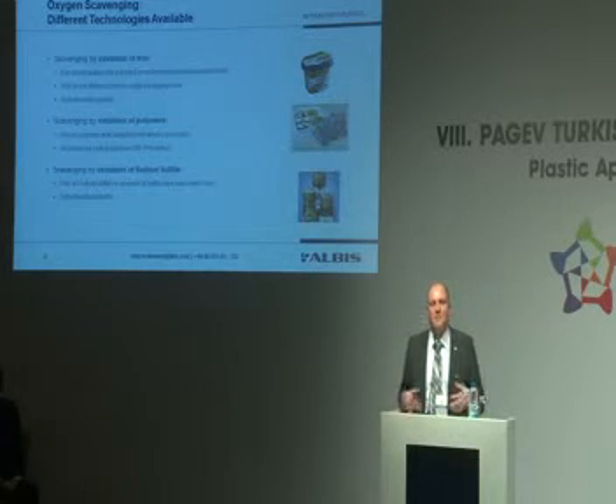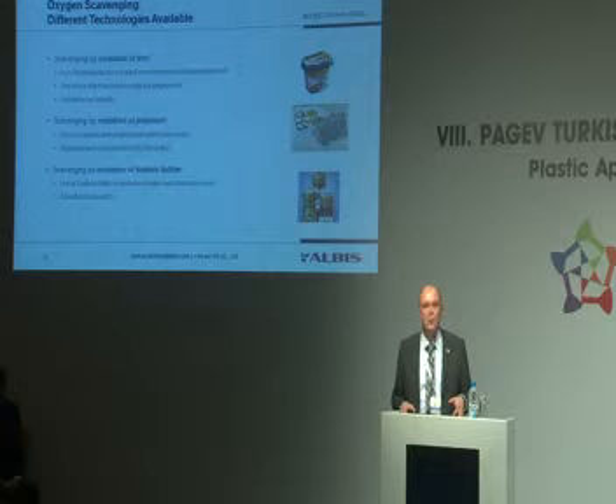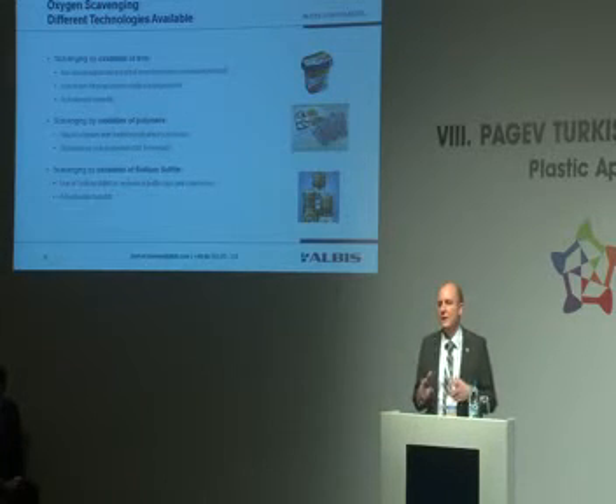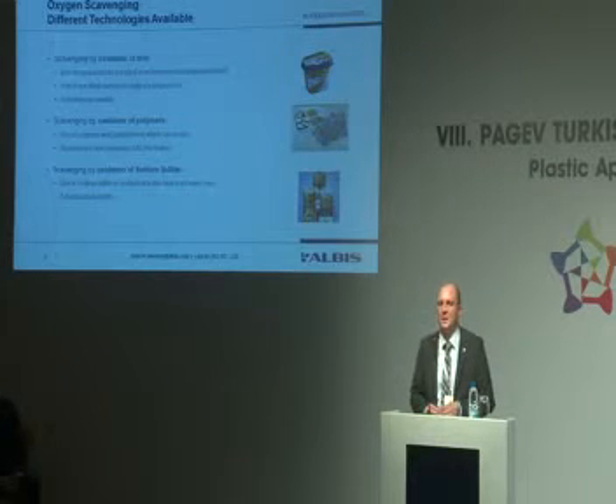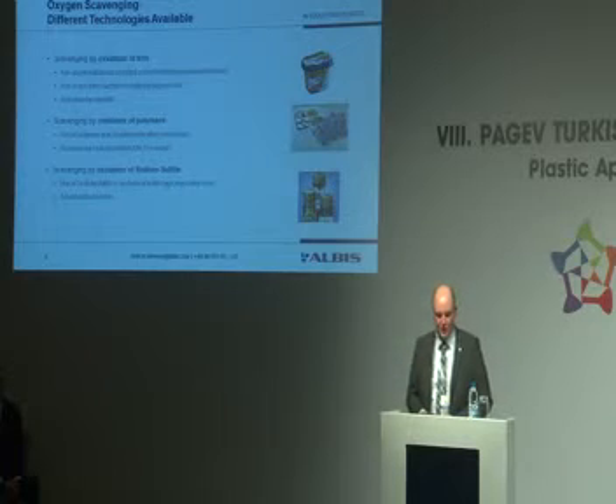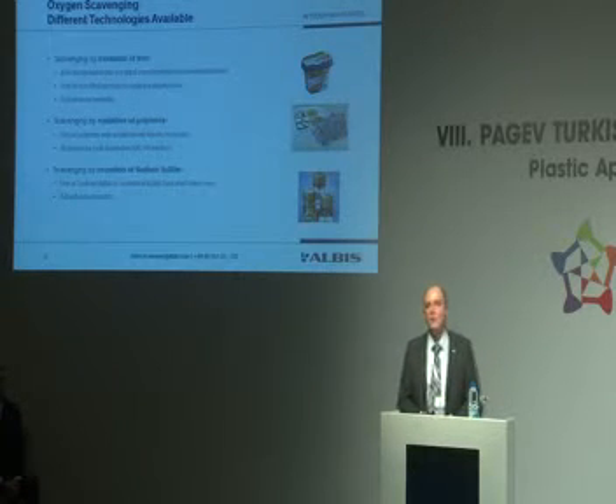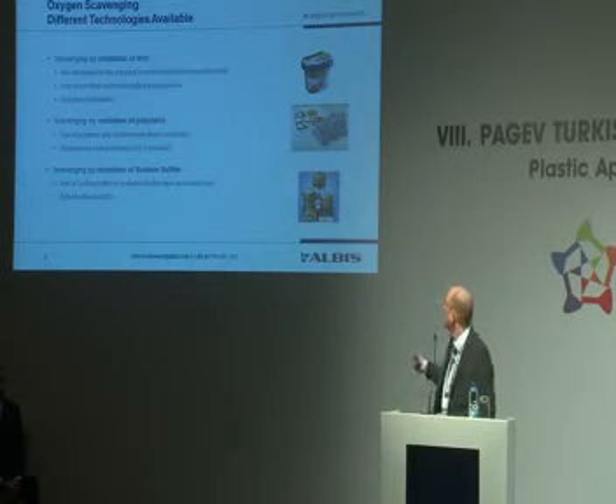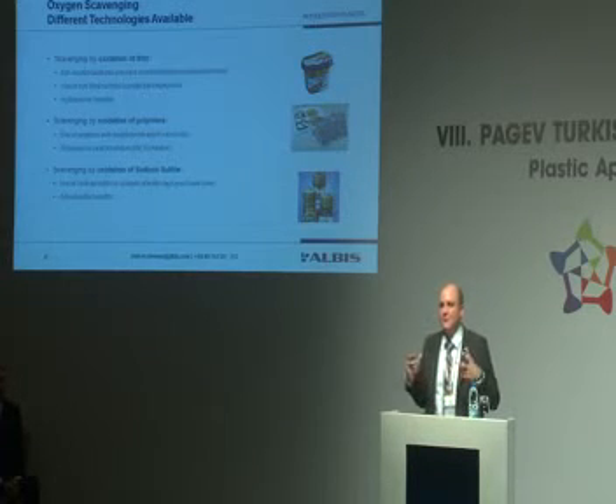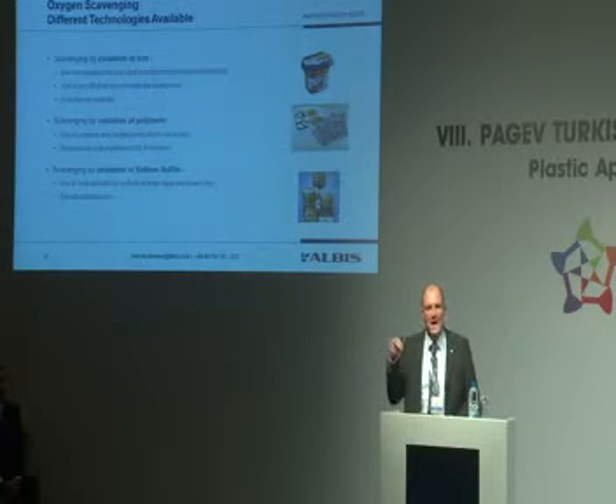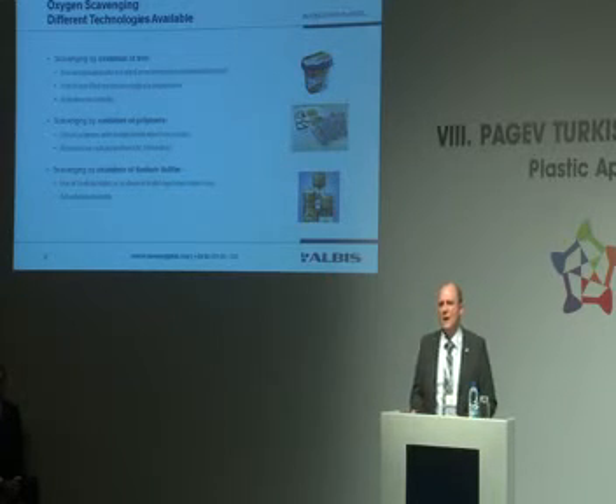This can be done these days commercially in two ways. One way is to add the iron through a packaging film. In the thickness of this film, the oxygen migrates to the iron and the absorption takes place. Another way is to use sachets, these small little bags filled with iron powder, and you add this to the packaging unit. This is something we find mainly in Asia.